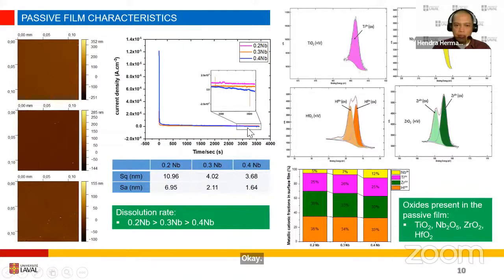and then we continue our analysis with X-ray photoelectron spectroscopy to check what is actually present in the thin film that forms on the surface. So there are titanium oxide, niobium oxide, hafnium oxide, and zirconium oxide. They mix together in this proportion.